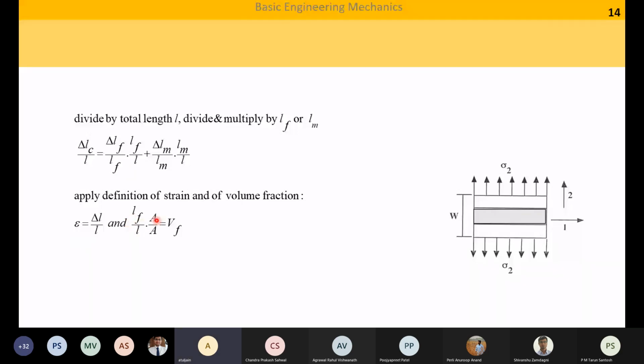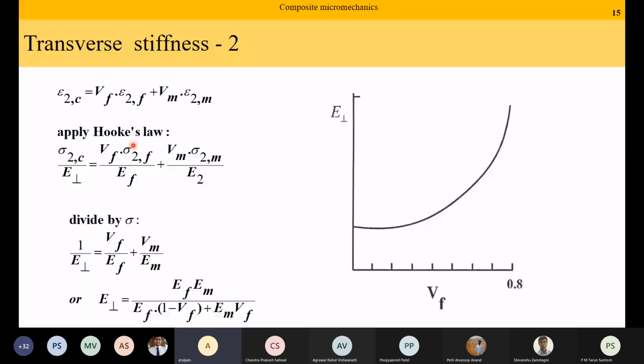LF into AF divided by L into A is your volume fraction. So, starting with this equation, I know that the strains are added. So strain in the composite is equal to volume fraction of the fiber into strain in the fiber plus volume fraction of the matrix into strain in the matrix. Apply Hooke's law, which says that epsilon 2 is equal to sigma 2 by EF, and you get this relationship. And we also know isostress, so we have said stress is the same, so I can delete these parts and I will get this relationship, that 1 by Young's modulus of the composite material is equal to Vf by Ef plus Vm by Em. Or you can also get this formula. This is known as inverse rule of mixtures.